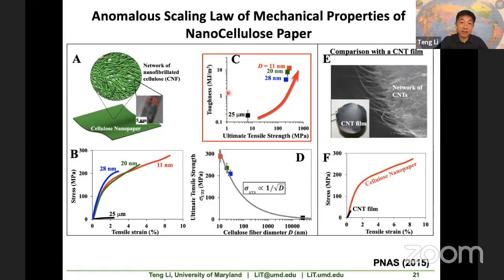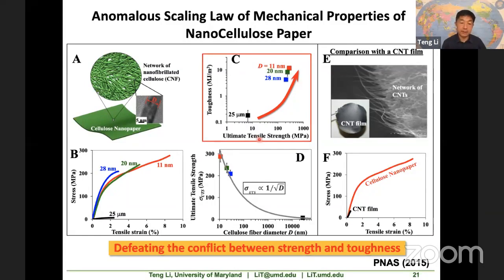We also did the fracture toughness measurement, and the difference between the regular paper and the nanopaper is more than 10 times as well. So this is the desirable scaling law, although it's not typical. And the increase is not small. So strength here increased 40 times, and the work of fracture increased 130 times, okay? So this clearly demonstrated that by decreasing the building block size, you can defeat the conflict between strength and toughness in paper. Now, of course, you don't want to stop here. You want to understand why, okay?